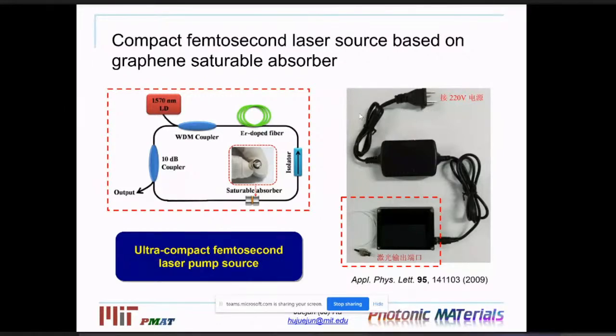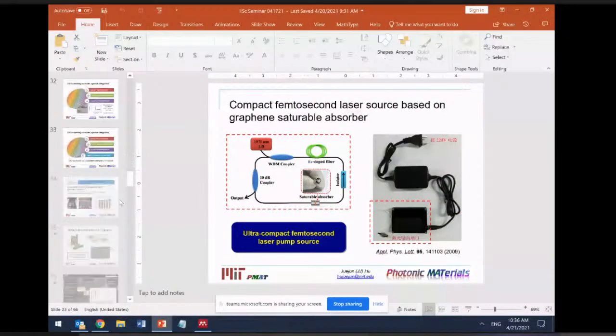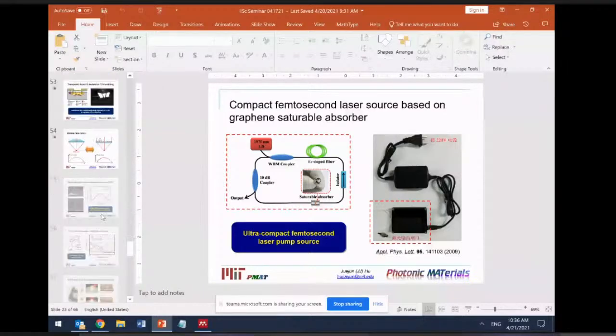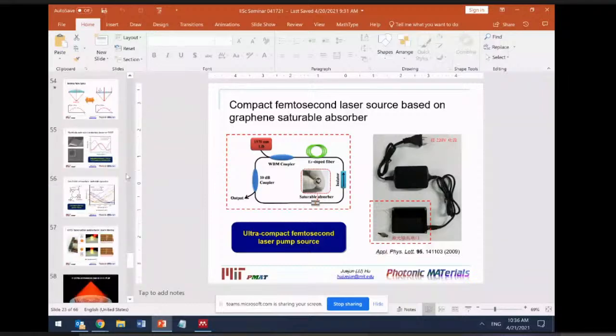JJ, I have one quick question on the temperature stability of these chalcogenide GSSTs. What is the maximum temperature that it can withstand? It depends a bit on duration. To trigger crystallization, we usually do it at about 250 degrees Celsius. At that temperature, it takes probably a few minutes. If you go to slightly higher temperature, you can expedite the reaction. It can go down to half a millisecond, like I mentioned. That's for the amorphous phase, so you can pretty safely use it below 200 degrees Celsius. Nothing is going to happen. For the crystalline state, it's thermodynamically stable, so you can heat it all the way up to the melting point, which is around 600 degrees Celsius.